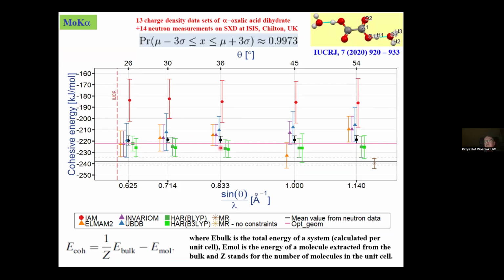All those tiny changes in values of hydrogen atom positions. Here you see the dependence of cohesive energy or crystal lattice energy on the used model of atomic electron density and on resolution. If we use neutron results as a reference, we are getting this kind of energy, slightly less than minus 240 kilojoules per mole. For Hirshfeld atom refinement, we are getting results which are more or less 12 kilojoules per mole worse. But for the independent atom model, we are 50 kilojoules per mole in error.